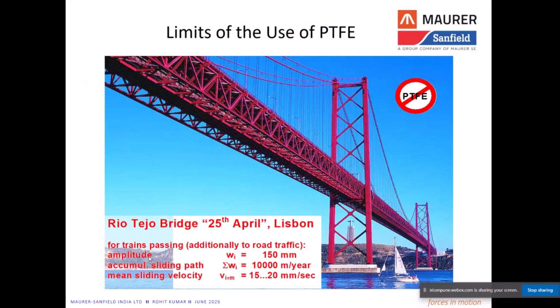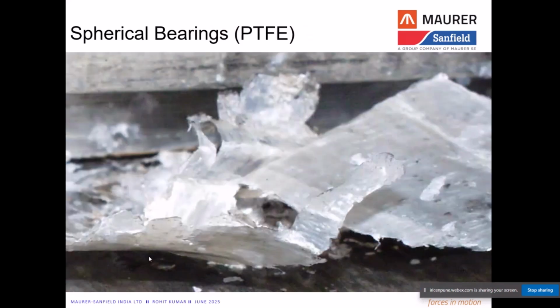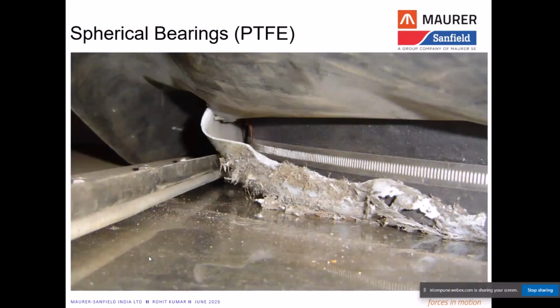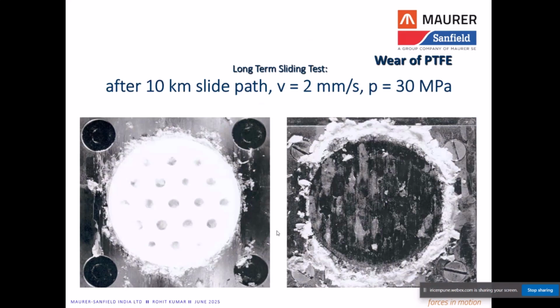If you can see, it's just an example: the Tejo Bridge in Lisbon. It's a rail-cum-road bridge where PTFE bearings are being used. But you can see in the images how the PTFE sheet has failed in the bearing. So this initiated the requirement of a new material which can at least avoid this kind of failure while also fulfilling the structural requirements. A test was conducted by the authorities to check the maximum capacity of this thermoplastic material.